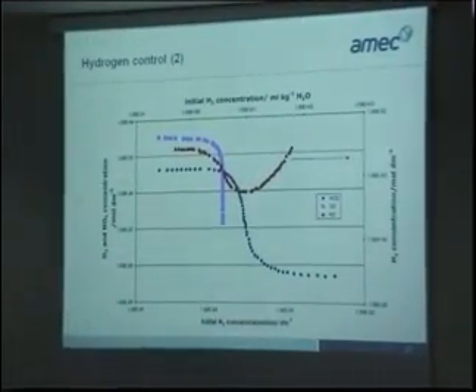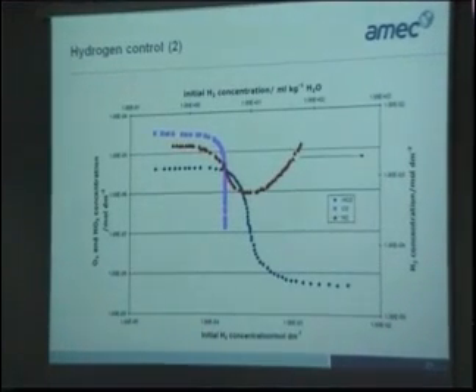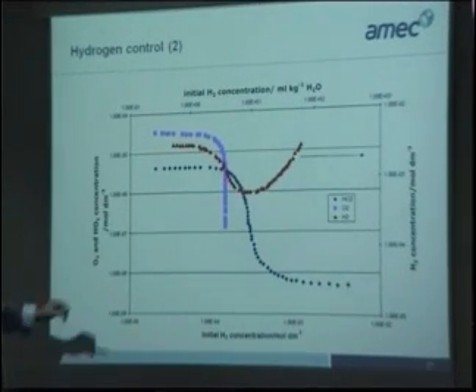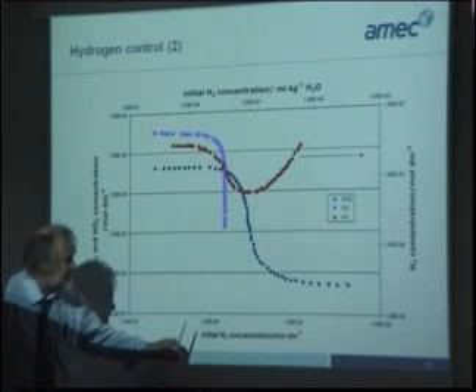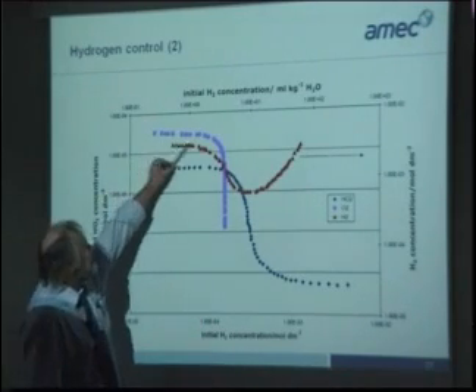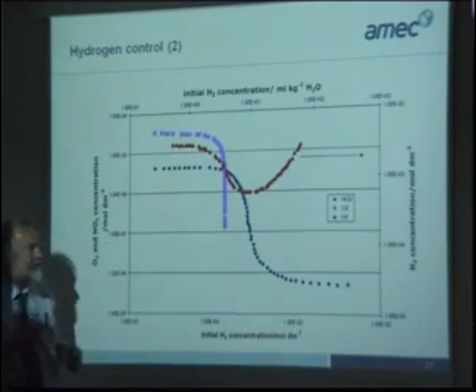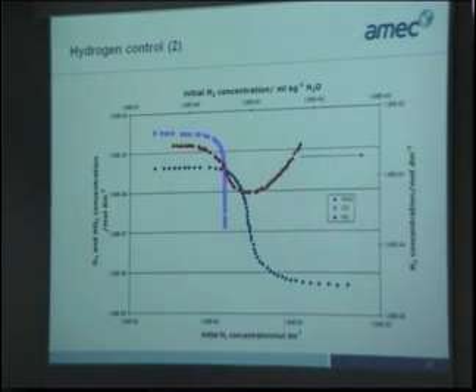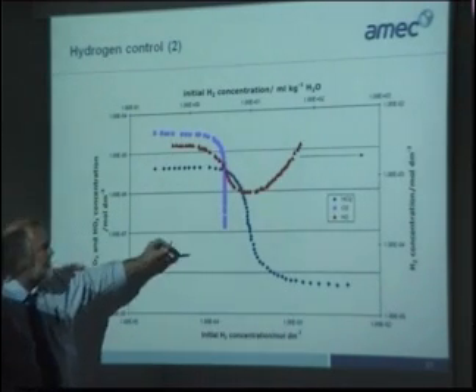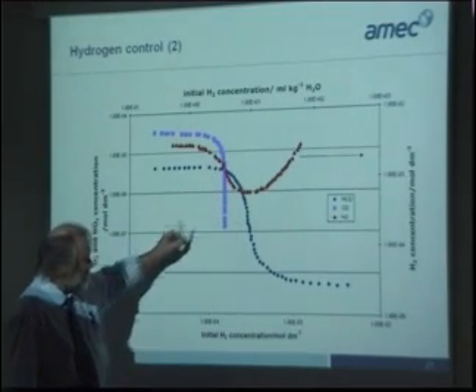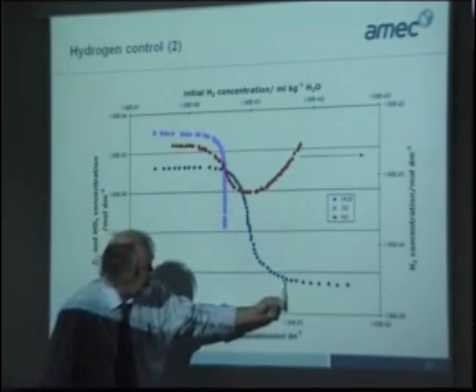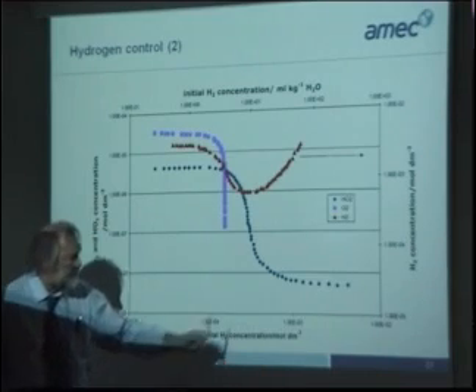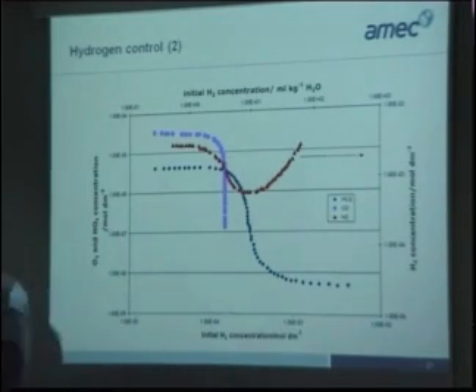Hydrogen will just mop up any excess oxygen that's there, but that's not its only function. If you look at this graph, you don't need that much hydrogen, in fact, to mop up the oxygen. It's the other free radicals that are doing the damage, the OH and the HO2. Here's the HO2. And we need quite a bit more hydrogen to bring that down to an acceptable level. So you'll find that plants will operate somewhere between 25 to 50 standard cc's per kilogram of hydrogen.